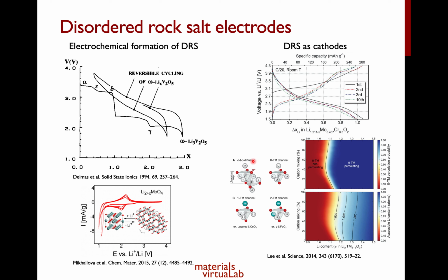Okay, so when you think about the rock salt, there are these tetrahedral sites that your lithium actually has to hop through when you transition from one octahedral site to another. Okay, they showed that if your tetrahedral site is surrounded by only lithium, the diffusion barriers are much lower than if you have at least one or even more transition metals surrounding that tetrahedral site. Now, in order for you to have a percolating network of zero transition metal type channels, you need a certain threshold of lithium excess to achieve that percolating network.